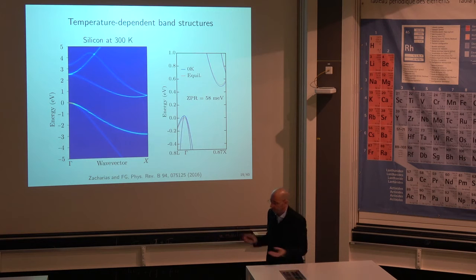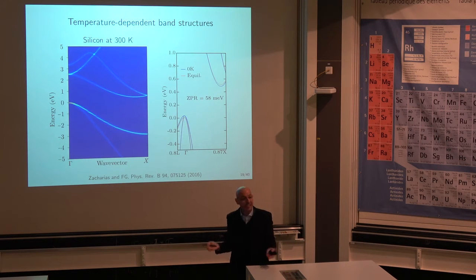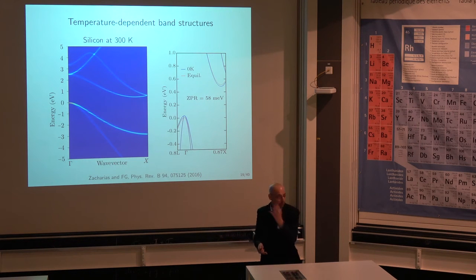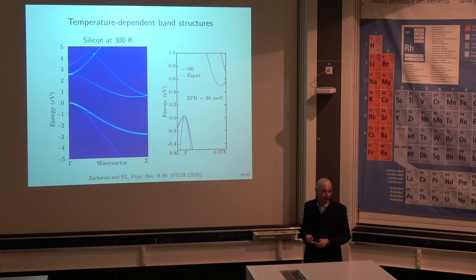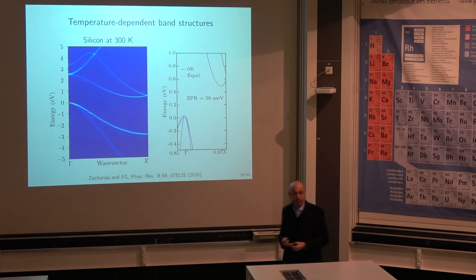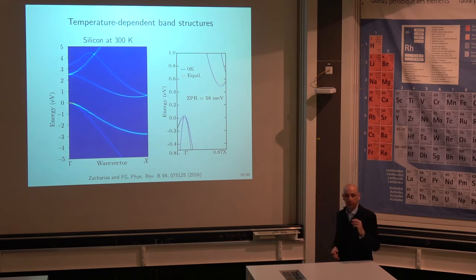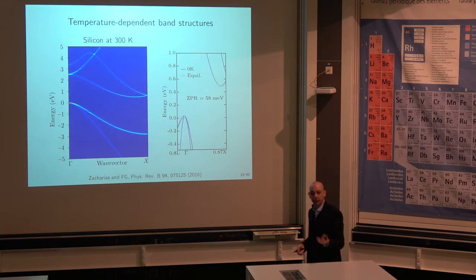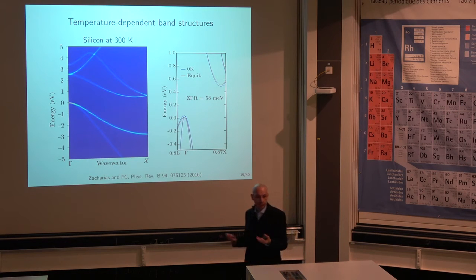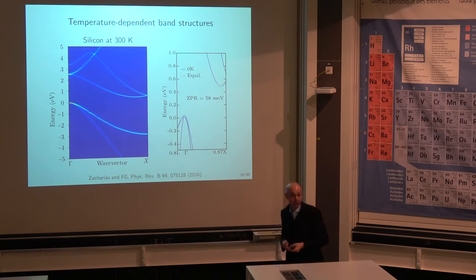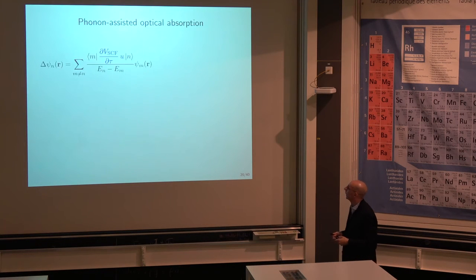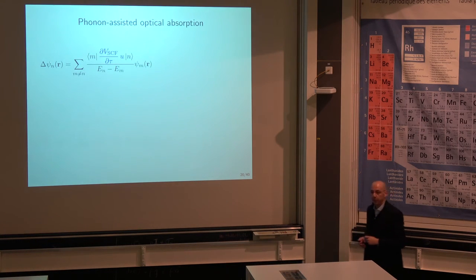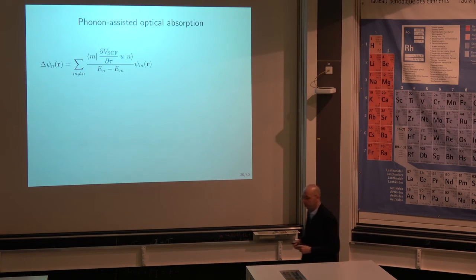Well, there are several reasons. For example, there are materials like diamond where the change in the band gap coming from this effect is of the order of half an electron volt. So that's something that is important and has to be taken into account. And there are other systems like topological insulators where you're working with band gaps of the order of 100, 200 millivolts. These kinds of changes can signify the difference between something which is or which is not a topological insulator. So that's quite important. Let me show you now the second bit, which is about optical properties.